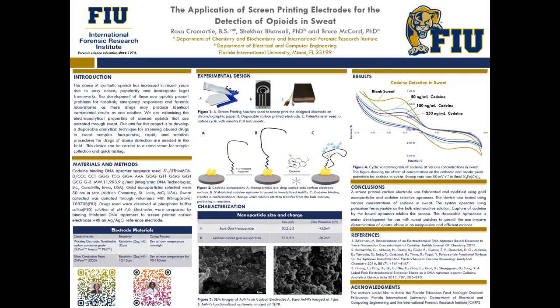In figure 2, we have a schematic design of how my target binds to the working electrode for the screen printed electrode. First, we have nanoparticles that were drop casted. The nanoparticles are the yellow that you can see, and the working electrode is the silver. It's supposed to come out black like carbon, but it's gray, which is the working electrode. We allowed the gold nanoparticle to immobilize onto the carbon surface. And after that, we followed by adding the thiolated aptamer. The thiolated aptamer can bind to the gold nanoparticle.